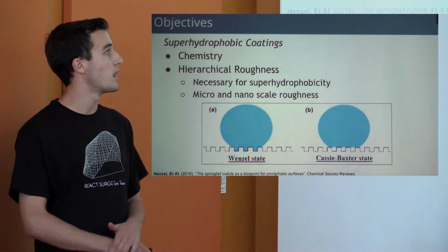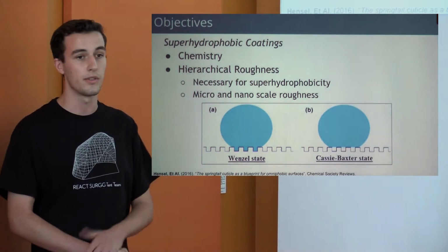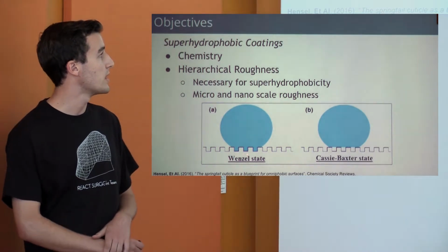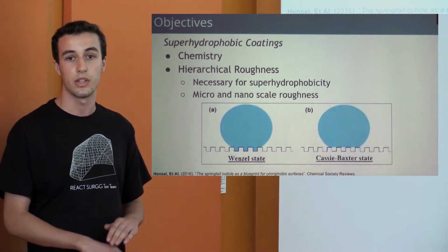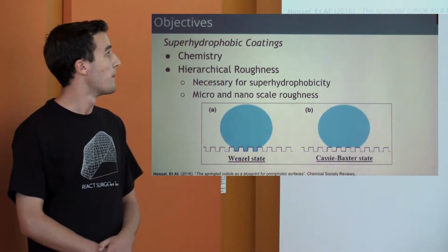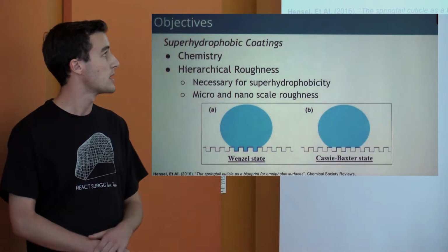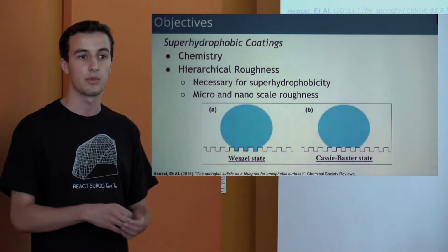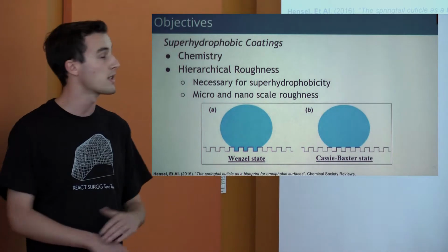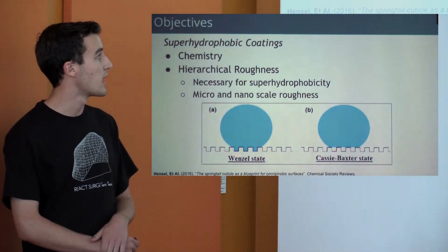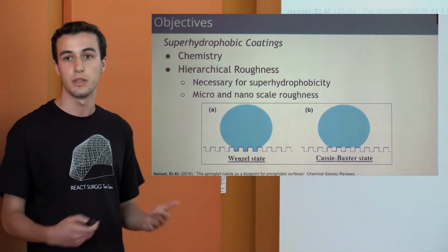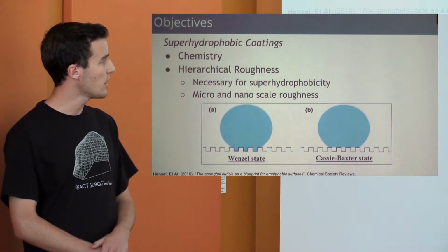Roughness can enhance the hydrophobicity of the surface in two different ways. One is the Wenzel state, where the roughness enhances the hydrophobicity simply by the water being in contact with a greater surface area due to the roughness. So if the surface was hydrophobic when flat, now that it's rough, it will be more hydrophobic.